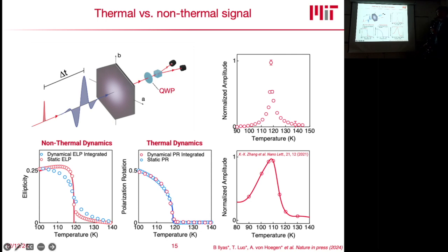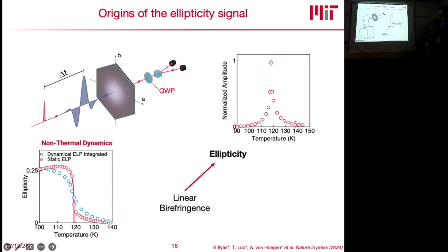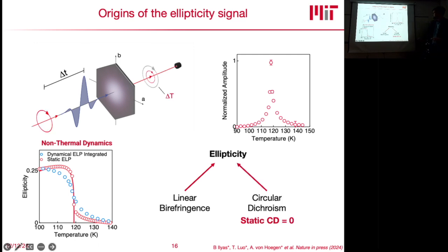And this is why I now want to focus on the ellipticity measurements and ask the question, okay, what is the cause of ellipticity in one of these optical experiments? For one, it's linear birefringence, right? If your refractive index along one crystal axis is different to the other one, your light starts turning elliptical if you come in. However, another aspect that can give you ellipticity is circular dichroism if you come in with linearly polarized light. However, in FPS, since it's a fully compensated antiferromagnet, the circular dichroism should be perfectly zero. So you do not have a static circular dichroism.